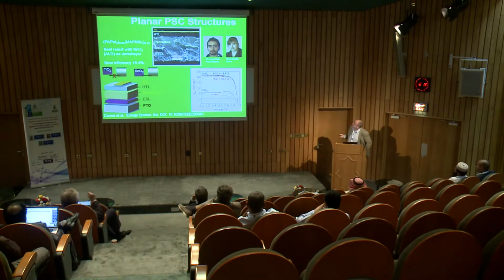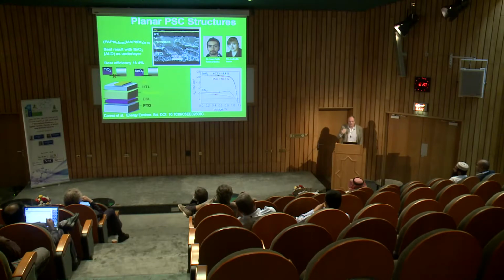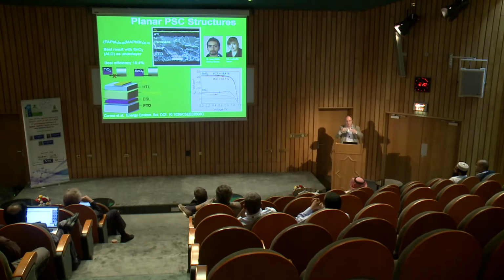This has of course been tried with moderate success, I would say. It's around 13-14% normally, with fairly problematic hysteresis. We had also here a project with my postdoc Juan Pablo and the PhD student Ludmila, who works with ALD deposition. And for some fundamental reasons, we wanted to try different contact layers. TiO2, as I said, is the obvious one, but we also wanted to see if we change the material to tin oxide, niobium oxide, what does it make to the cell, to understand.